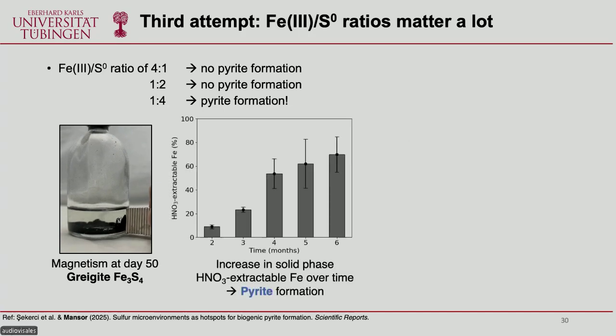Then we use a technique called nitric acid extractable iron. So most of the iron minerals that I've mentioned all dissolve in hydrochloric acid. And so we can dissolve them, we can remove them, and then what's remaining is pyrite, which is only dissolvable in nitric acid. And so we quantify that. We can see that within the first 2 months, already there's some pyrite forming. But within 6 months, it's very clear. Pyrite formation is about 70% of the total iron in the system.